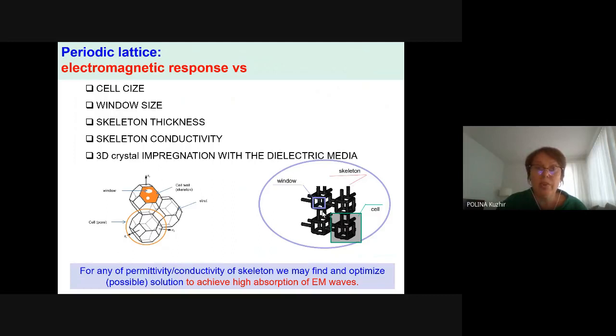So I want to tell you that if you deal with material composed of cells with open porosity, and you address an electromagnetic wave which corresponds to the cell size and window size, you may expect resonance behavior, electromagnetic behavior, like for instance resonance electromagnetic absorption. But you should also remember the conductivity of the skeleton and its thickness. Of course, if the skeleton is too thick and too conductive, it will behave as a bulk metal.